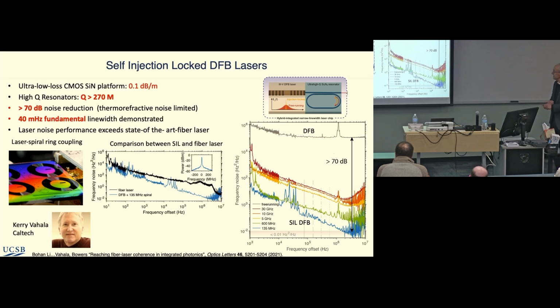What you see here is the frequency noise out of a standard DFB laser. It's about a megahertz linewidth laser, that's about what you expect. But when you couple it to these high Q rings, it self-injection locks. This gain region injection locks this high Q cavity.